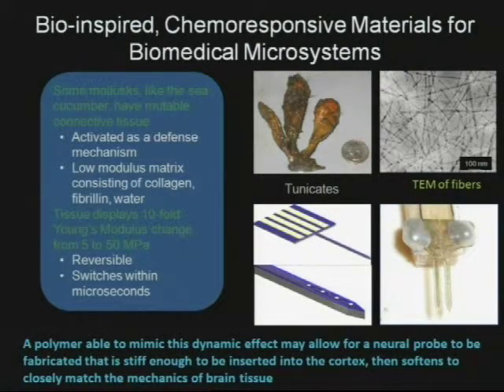And if you were to scour the literature, you'd see there's a number of approaches already in play, some built on silicon as the primary structural material, others built on conventional polymers. But we have collaborators here at CASE that have developed a polymer that exhibits a chemoresponsive behavior, meaning that when it's exposed to moisture, its modulus, Young's modulus, reduces by about 3 to 4 orders of magnitude. We're envisioning this kind of a polymeric system to be ideal for a cortical implant, where you would like the implant to be stiff upon insertion, because literally the surgeon would implant it into the brain through the tissue, then after insertion become compliant to the tissue, and in an ideal sense match the mechanical properties of the tissue.